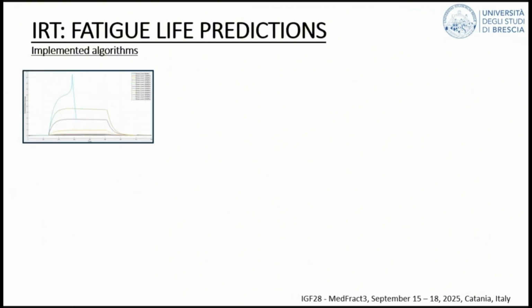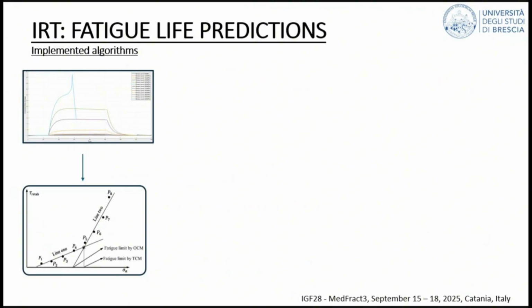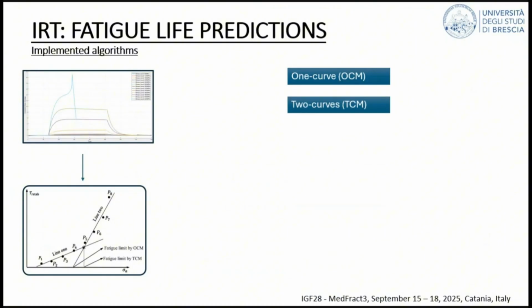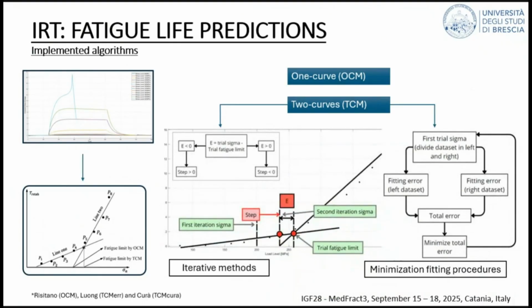Now, having all these thermal indexes, we follow what is usually done in the literature. So they are most often plotted against the applied stress. So what you get is a diagram which qualitatively looks like this, where you have 2 main regions. And then there are different strategies that you can use to, let's say, identify the fatigue limit, which is associated with the transition from the first region to the second one. And there are different methods in literature.